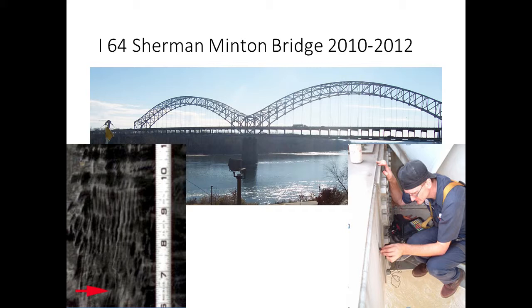We took this picture, which shows a crack that's in the web of the box beam at a transition butt weld for the bolted field splices. The crack's about over 2 inches long there. We also did strain gauging, and at that time our strain gauging results indicated that the live stresses were too low and fatigue wasn't going to be an issue.